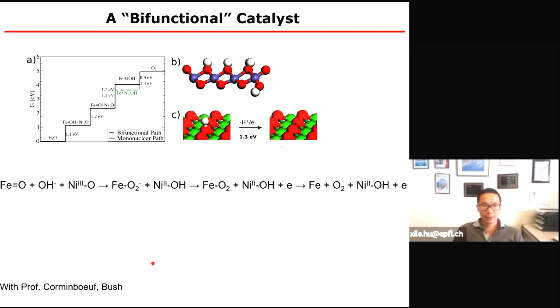And we realize that such a structure may enable something that is mechanistically different. So if we consider iron as the active site, we can make iron oxo species, so that's fine by computation. Then the hydroxy attack on iron to make iron OOH is actually now having a really high energy, 1.7 eV. And so this will be the potential determining step, and so iron will not be a good catalyst. But if we now have a two-component where we have a nickel OH nearby as a second component, we realize that when the hydroxy is immediately transferred to a site on nickel, this is a nickel site, nickel center, where the oxygen now is a good hydrogen atom acceptor. So you take hydrogen, then we can actually lower the energy pathway.